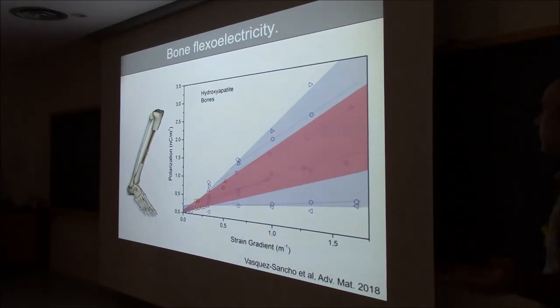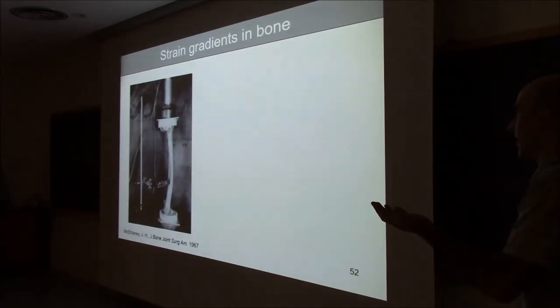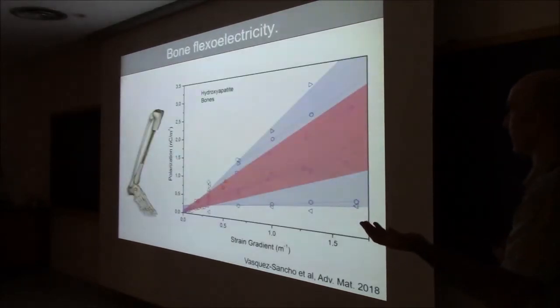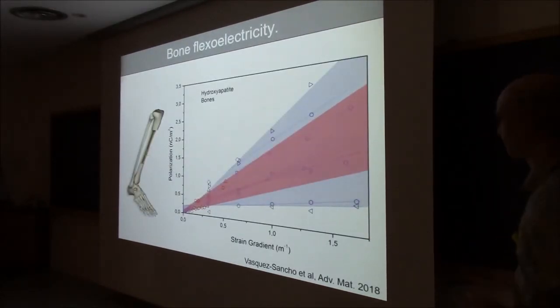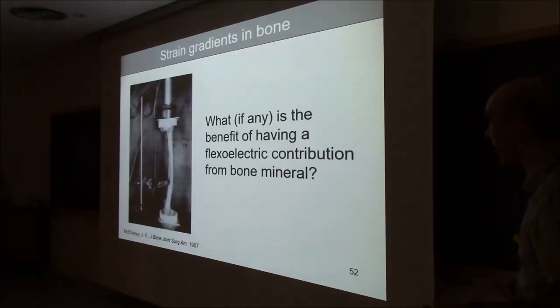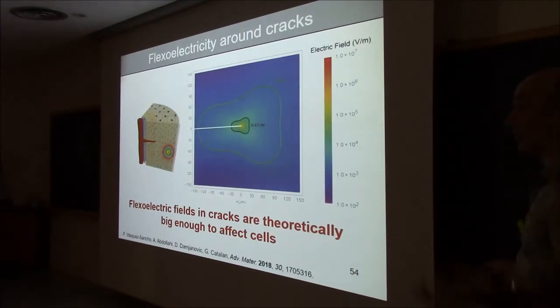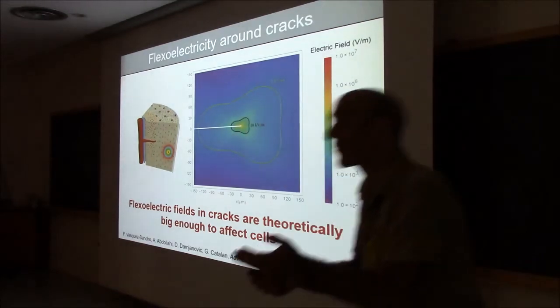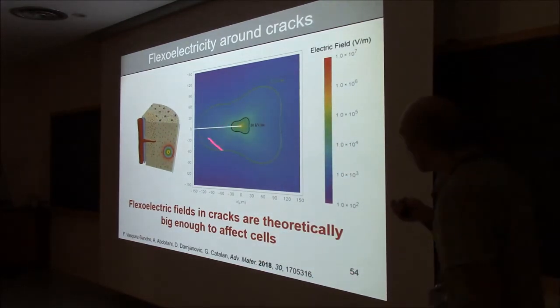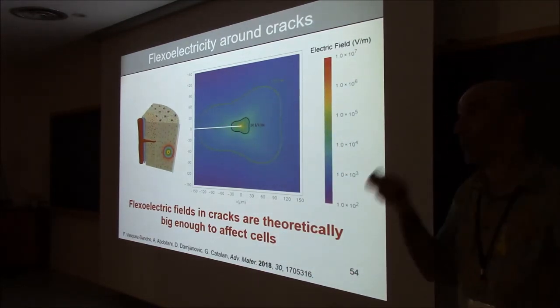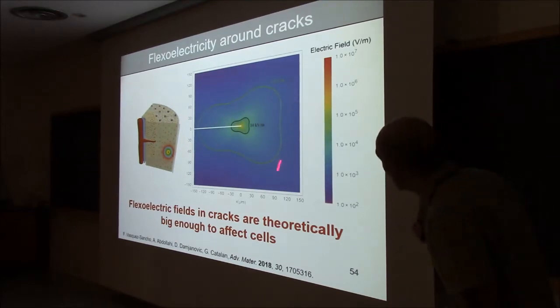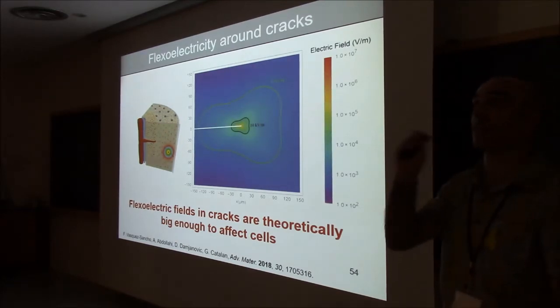Bones, since we've talked about cracks, and I've said that bones are flexoelectric. They are not very flexoelectric. The actual flexoelectric coefficient of bones is not that big. But remember that in cracks you have very big strain gradients, so that small flexoelectric coefficient multiplied by the strain gradient of your bone is big enough to really affect the cells near the bone.